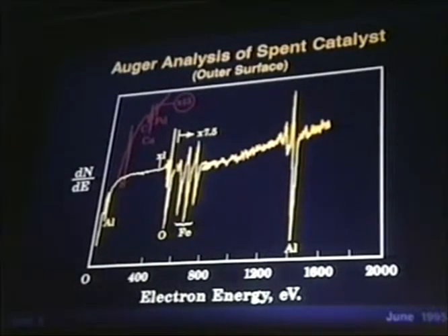These figures show that the spent catalyst got deactivated by a surface deposition of iron, which nominally was covering about 80% of the available palladium surface. The iron concentration on the inside of the pellets, when we looked at it, was small, but so was the palladium concentration as well. That is the way the catalyst was designed for this liquid phase operation. Hence, it was concluded that iron in a dissolved form in the feedstock was the main culprit responsible for the catalyst deactivation.